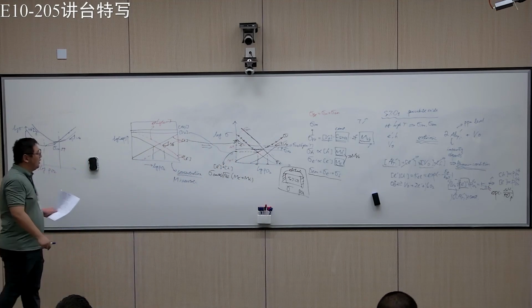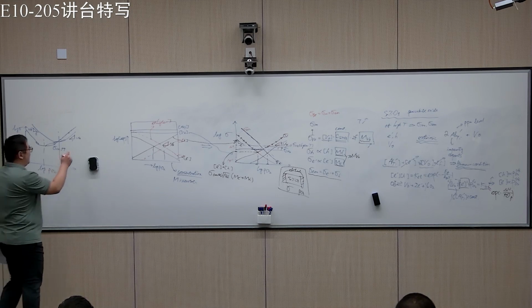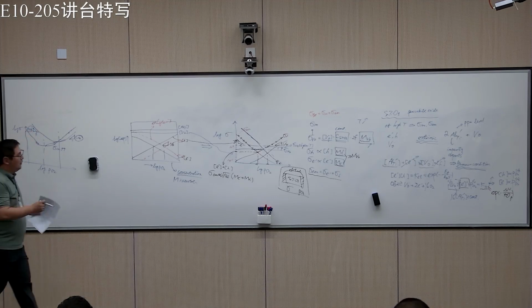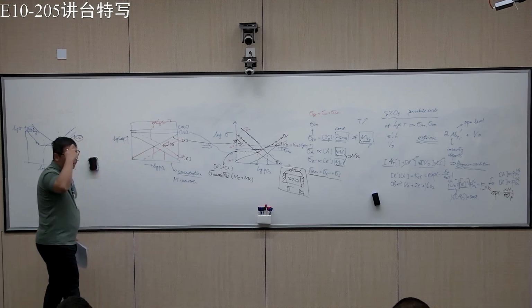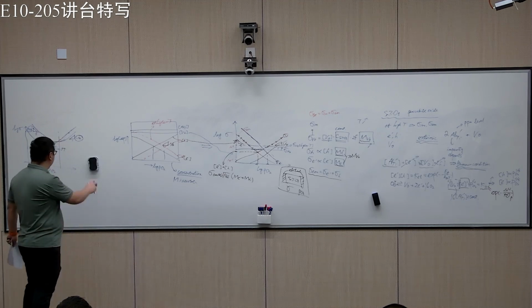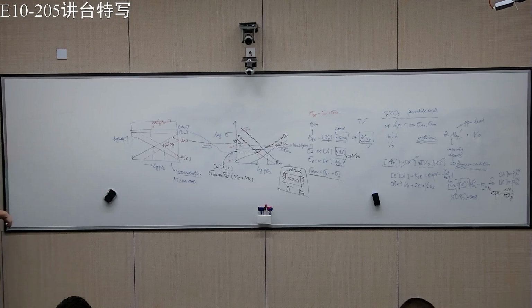However, let me just quickly summarize what we discussed. Essentially, it gives you another way of knowing the Brouwer diagram. You'll see that this power law, -1/4, is actually like a fingerprint for what kind of defect chemical reaction you have. You can summarize the principles. For example, you have defect concentration scaling as PO2 to the power n.